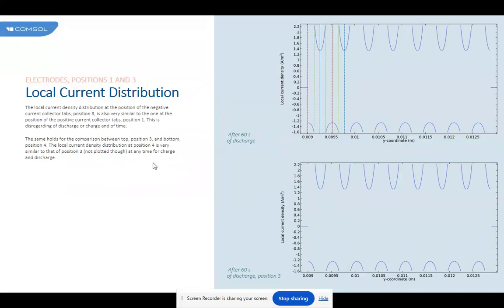The local current density distribution at the position of the negative current collector tabs, position 3, is also very similar to the one at the position of the positive current collector tabs, position 1. This is regardless of discharge or charge and of time. The same holds for the comparison between top, position 3, and bottom, position 4. The local current density distribution at position 4 is very similar to position 3 at any time for charge and discharge.